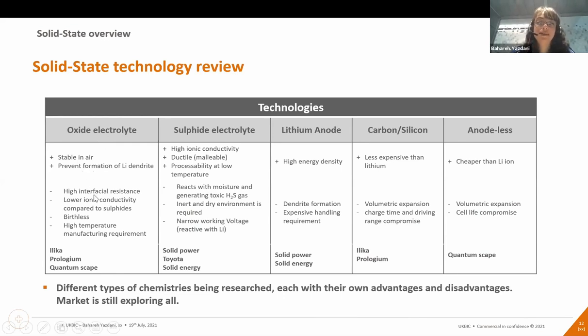So they are stable in air and prevent lithium dendrites because they are rigid and solid. So they prevent the lithium dendrite, which is one of the important challenges and main problems with using lithium metal, which oxide-based electrolytes can address. But there is high interfacial resistance and brittleness. So you can see lots of companies working on different technologies, including sulfide electrolyte and lithium anodes, and some companies using different approaches for the anode side.